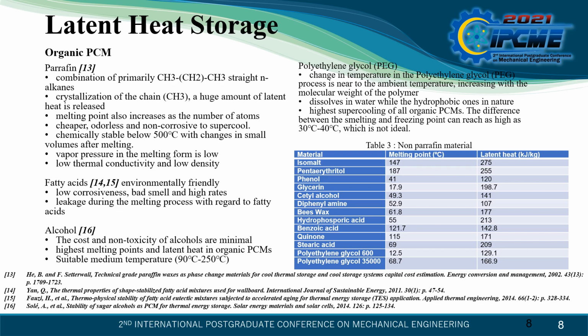Polyethylene glycol, PEG. The change in temperature in the PEG process is near the ambient temperature, increasing with the molecular weight of the polymer. It dissolves in water, while the others are hydrophobic in nature. It has the highest supercooling of all organic PCMs, which is a disadvantage. The difference between the melting and freezing point can reach as high as 30 to 40 degrees Celsius, which is not ideal. Table 3 shows examples of non-paraffin materials.